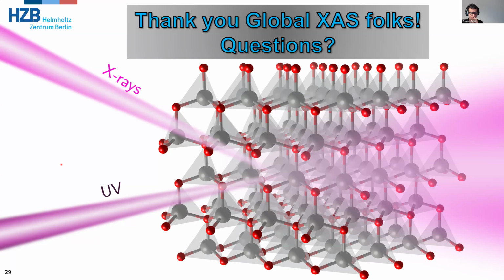Then you're asking a very interesting question for the zinc oxide. For the experiment that I've shown here, the pump actually generates quite a lot of carriers, typically above the Mott density. Being above the Mott density means that the optical excitons cannot form in zinc oxide. You actually keep something that is pretty plasma-like, let's say, and this is interacting with your core excitons that you generate with your probe pulse. Does that address your question? Yeah. Thank you so much. So it's in a specific electronic state.